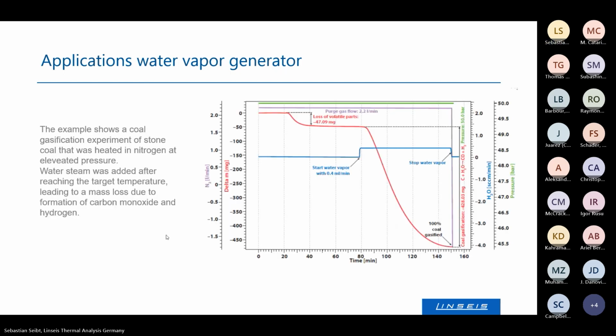The main application we do a lot, and are always asked about when we speak of steam, is coal gasification or biomass gasification, where you heat a carbon containing sample in a water containing atmosphere to get a so-called gasification reaction. This graph on the right shows what happens - this is one of our reactions.